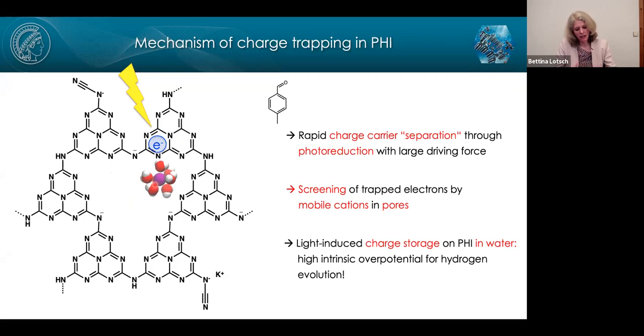So we believe there's actually a role of these cations in the pores in screening the electrons that are dumped on the carbon nitride backbone by photoreduction. Now, at that point, let me mention that this is quite peculiar because these carbon nitrides are known to be good hydrogen evolution catalysts. And from good hydrogen evolution catalysts, you would expect that they don't trap electrons on the backbone, but give them off to the electrolyte very easily to reduce protons. But this is not what is happening here. On the contrary, we're actually trapping these electrons in aqueous solution.